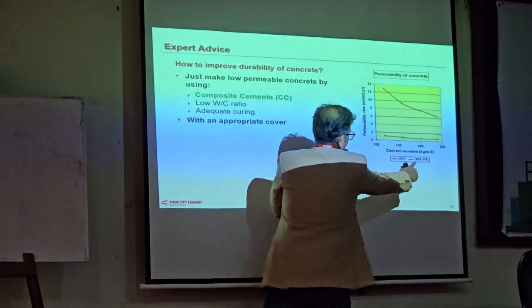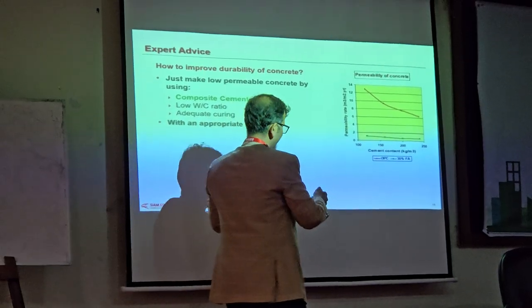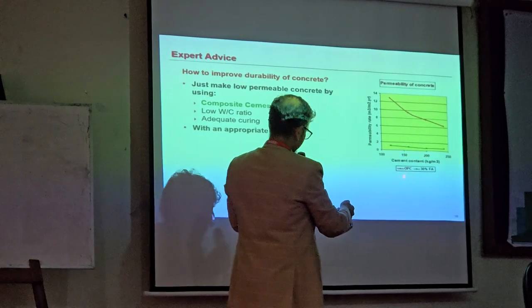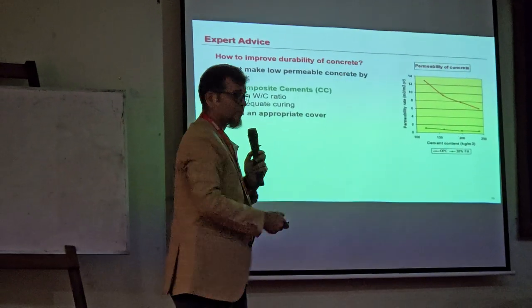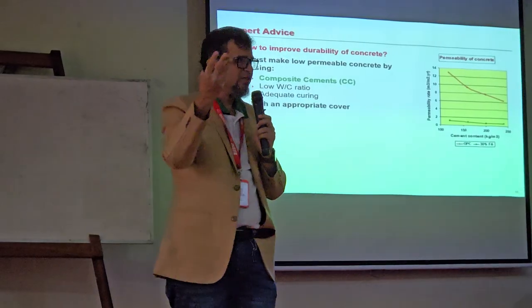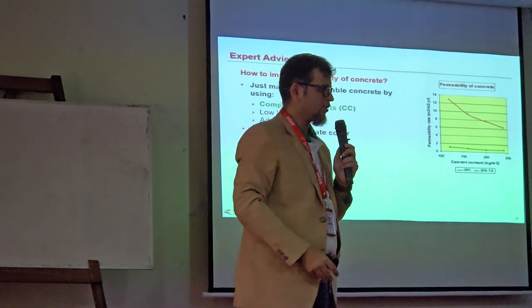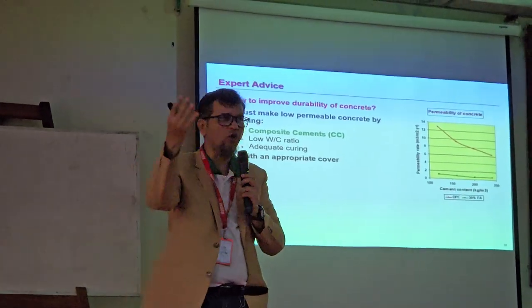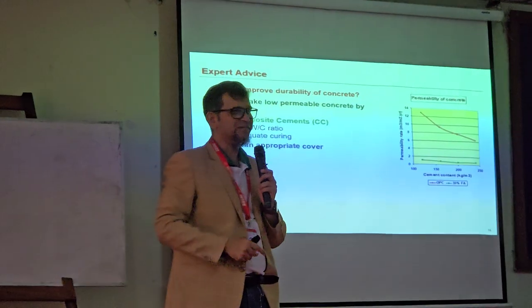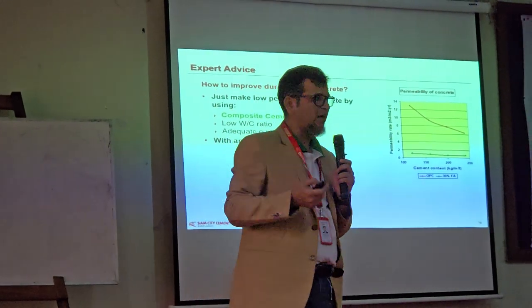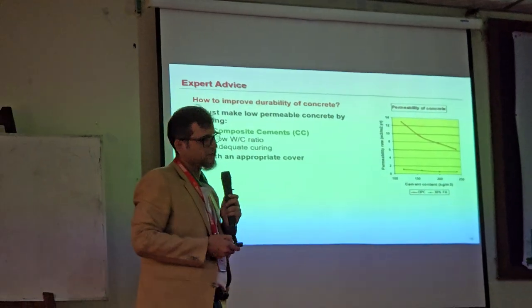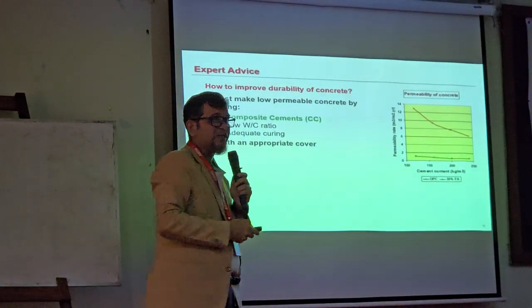So this is one research I found from an Indian YouTube channel: if there is 30% fly ash in the cement, the permeability is here. And if there is no fly ash, as happens in the case of OPC, the concrete becomes very permeable and it intakes moisture from the environment. When rain comes, it takes the water in. When there is moisture in the air, it takes the water in. When there is fog or mist in the winter, it takes the moisture in. And it lets the moisture reach the rebar, and the rebar becomes rusty. The iron becomes ferric chloride, ferric sulfate, ferric oxide, whatsoever, and the bond between the rebar and the concrete goes off.